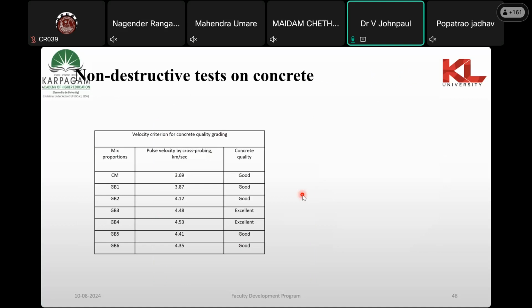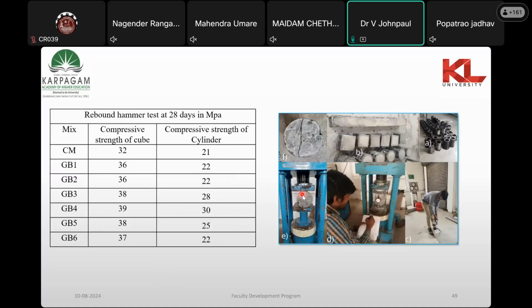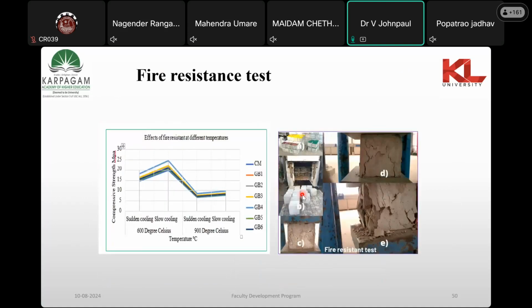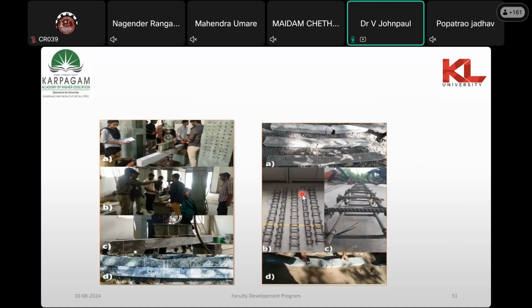And these are the UPV test method results and the compressive strength. Then this is the fire resistance test, done for the control mix and the GGBS-based mix. They exhibit similar properties, but even after going to 900 degrees Celsius in the oven, the GGBS mix exhibits good strength capacity compared to the control mix.